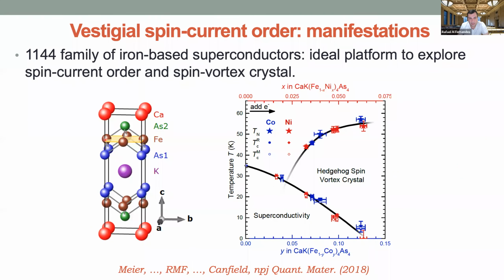So you see that this is a bilayer system, and the layers are separated by a potassium atom in the middle and calcium above. So this arsenic here sees calcium, and this one sees potassium—sorry, this one sees calcium. So these two arsenics are different. This is an explicit symmetry breaking by the crystal field.